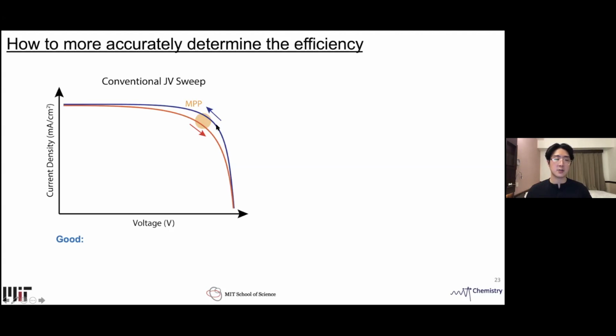Now, the advantage of using a conventional JV sweep, which is just sweeping the voltage and measuring the current or current density, is that it is simple and fast. However, the downside is that the power conversion efficiency measured or extracted is sweep rate sensitive, or sweep rate dependent, and as a result it is difficult to extract the true efficiency.